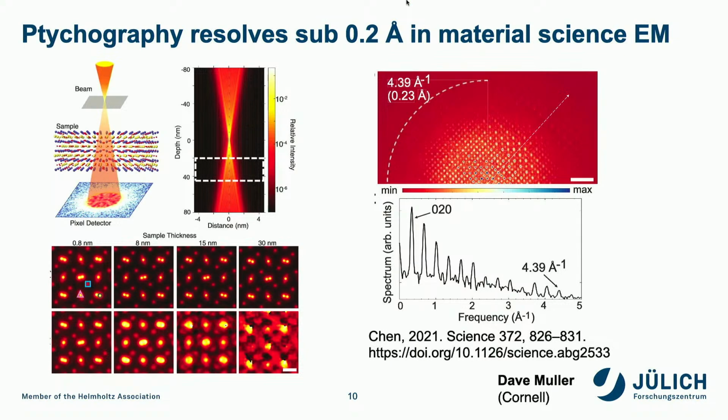It's obtained on scandium rare earth scandates, particular crystals where they measure these small distances. And of course they employ 10,000 times the dose that we are using. So obviously it's not a fair comparison, but still this technology has really enabled this, and it's close to the diffraction limit. In this case, this study was limited by the thermal vibrations of the individual atoms.